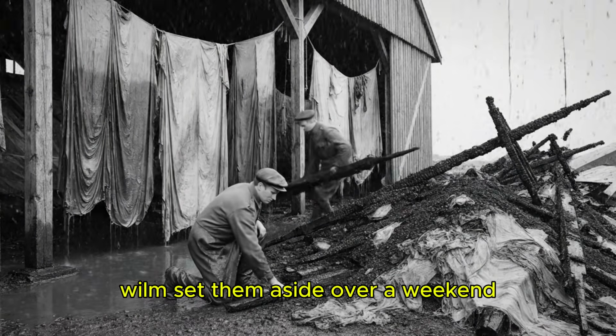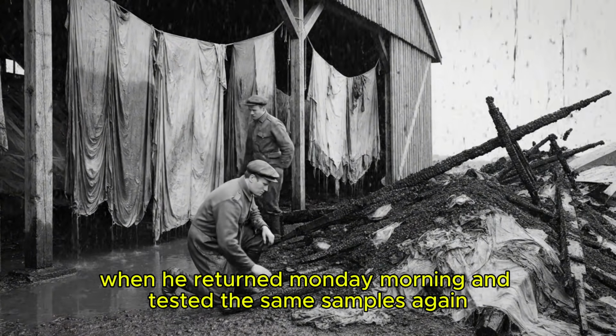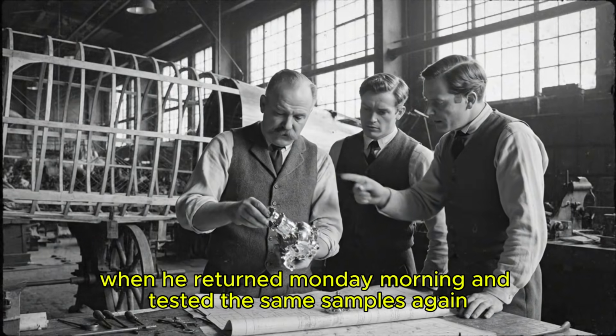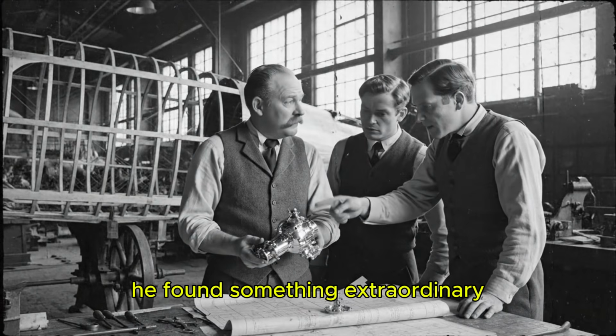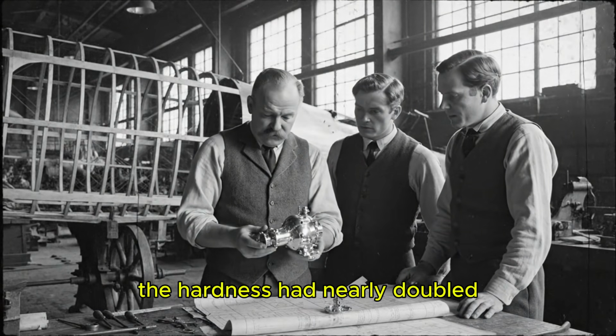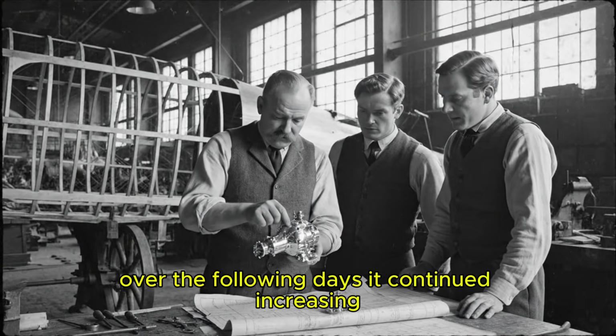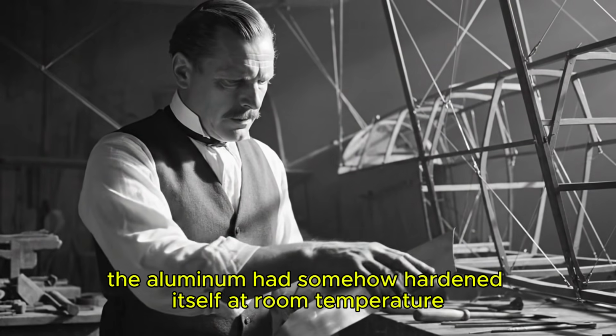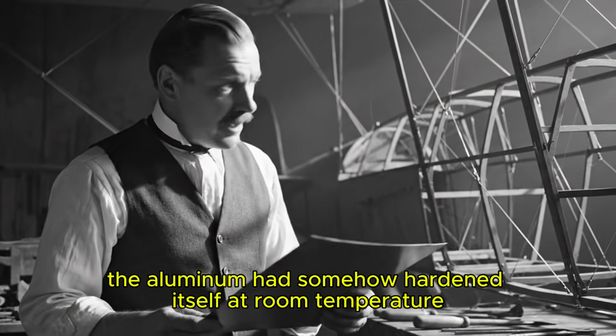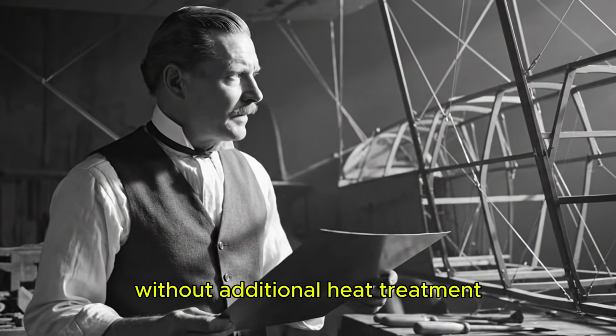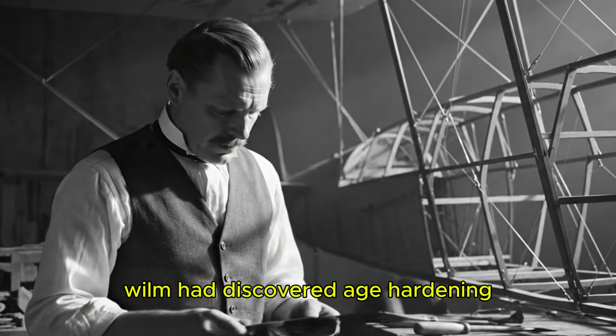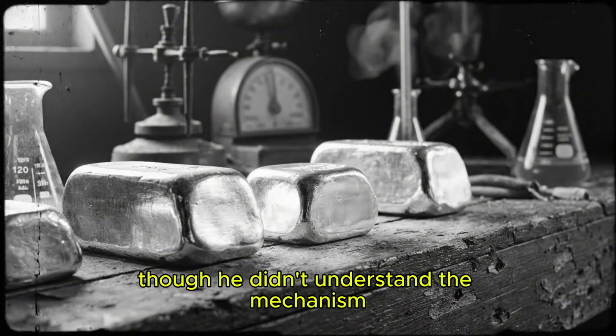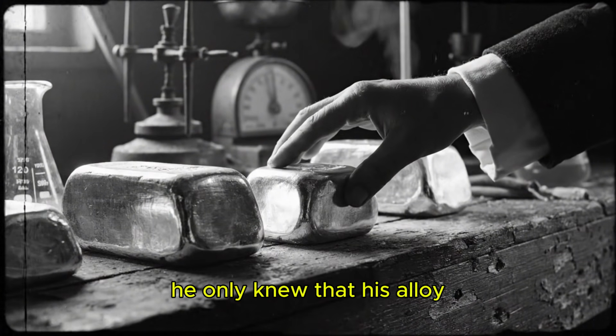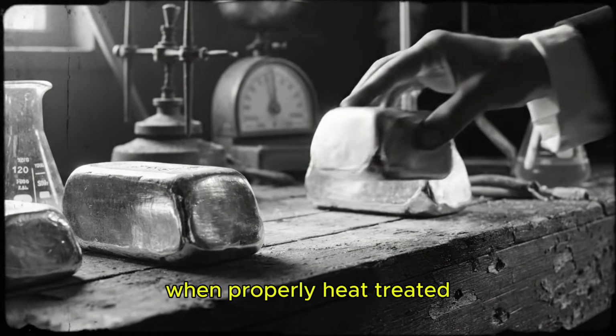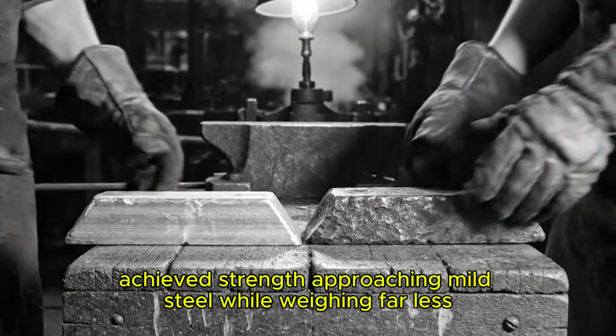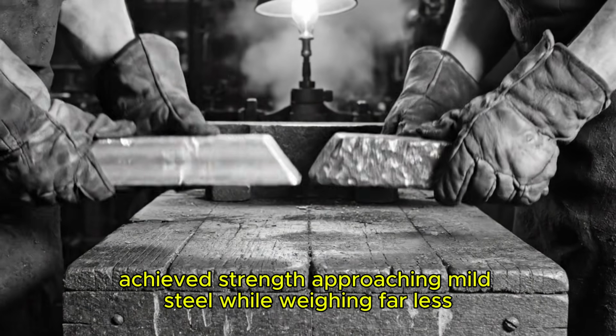Over a weekend. When he returned Monday morning and tested the same samples again, he found something extraordinary. The hardness had nearly doubled. Over the following days, it continued increasing. The aluminum had somehow hardened itself at room temperature without additional heat treatment. Wilm had discovered age hardening, though he didn't understand the mechanism. He only knew that his alloy, when properly heat treated, achieved strength approaching mild steel while weighing far less.